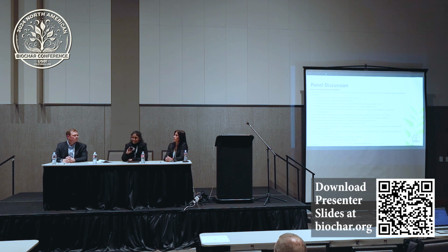Others? I just want to add one more point, or maybe two more. So the hydrophobicity and hydrophilicity of the biochar also plays a very important role in the adsorption. It's because there is electrical conductivity that a lot of the time we don't give enough importance to it. But when it comes to the bioremediation, electrical conductivity plays a very important role because of the redox state, the way it switches.